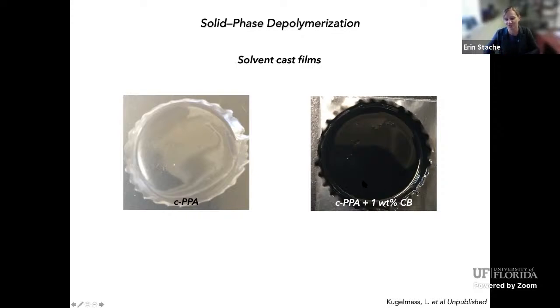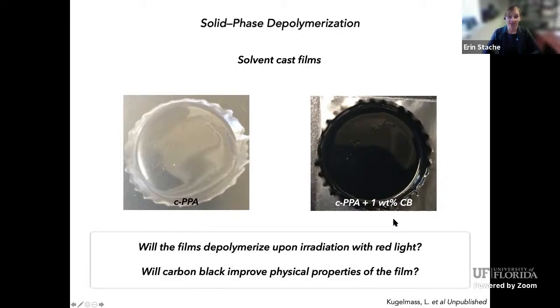And then this is what it looks like with just 1 weight % carbon black. We've gone lower, to like 0.5%, and it's still sort of midnight black, but very, very well dispersed and well suspended in the polymer film. And so the question is, all right, is this still going to work once we move to solid phase? It worked really well in solution, but you have a lot of chain mobility.